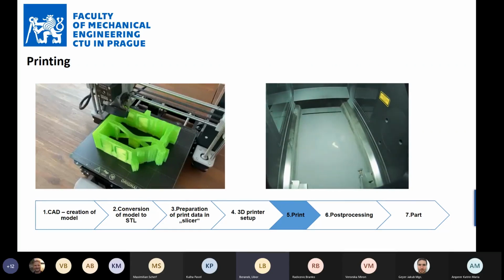The recoater is a mechanism which takes the powder from the powder container and spreads it with a certain width. Usually the layer height we use is something like 40 or 50 micrometers, 0.05 millimeter.